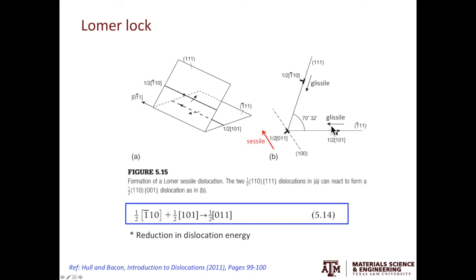If we do a simple addition as shown in the blue box, you will get the final dislocation Burgers vector as 0-1-1. Before meeting each other, these two dislocations will glissile, means they were able to freely move on the slip plane. However, after combining into another dislocation, the dislocation Burgers vector is not on the slip plane anymore. Then the configuration is sessile, means it's immobile.